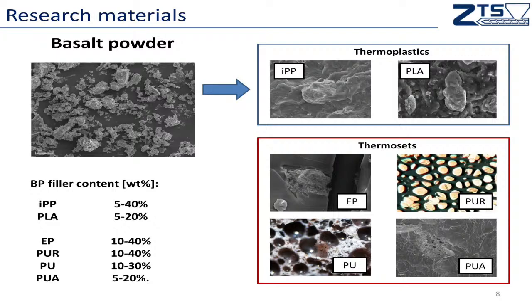As I said, thermoplastic polymers such as polypropylene, the typical non-polar material with a high ability to create crystalline domains, and PLA, the most commonly used and most perspective biodegradable polymer in the industry. Then we move to the thermosets, the materials that should be replaced as fast as possible. Developing different highly filled composites gives an opportunity to reduce the amount of these non-biodegradable materials. We use the epoxy resin, which is mainly known from the production of lightweight constructions and composites reinforced